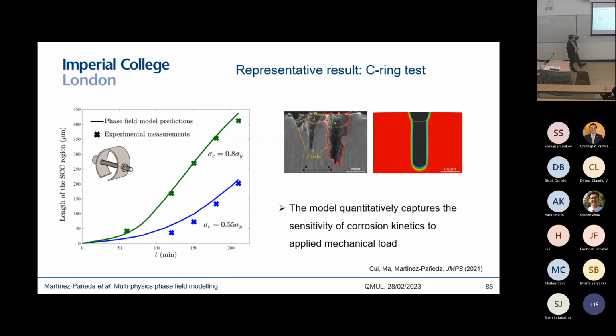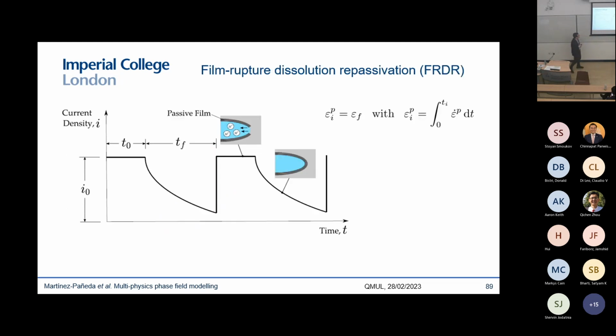And you can see here some experimental results, so a comparison with experiments. You can see that we are able to capture very well, we get a very good agreement with experiments conducted at two very different applied loads. And you can see that we also get a very good agreement in terms of the morphology of the defect, of the pit, right? So these two images are on the same scale. And you can see that we only focus on one pit, but we could have modeled those other pits, and you can see that we get a very good agreement.